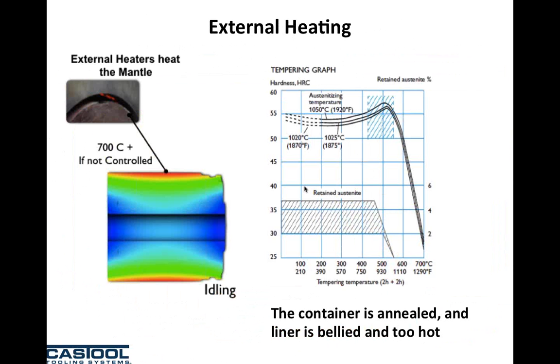And also, when people try to heat up the container, there are several options, and we see a lot of people still use external heaters. In order for the liner to be at extrusion temperature, you need to have a high temperature from the container shell, which can be around 700 degrees Celsius. And we know even for hot work tool steel, H13 would not be able to withstand that temperature for a long time, and you're going to anneal the container. When you anneal the container, the mechanical strength or integrity of the container is gone. When you extrude, the liner is going to be bellied. And because of the profile, it's hotter outside and colder inside, you're going to see temperature swings and temperature changes. And the liner can be too hot during extrusion as well.